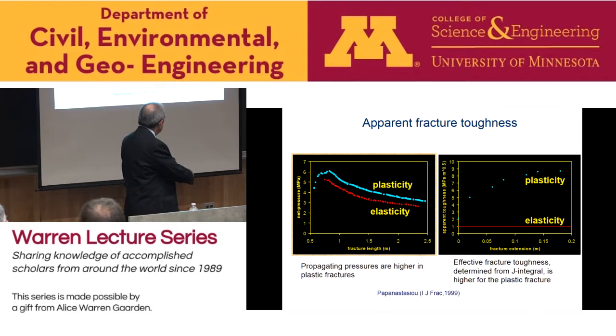And we use one of the energy criteria, the J integral. Basically, we propagated the fracture with a cohesive model, but at the same time, we took contours of J integral, and it was possible to calculate this increase in the apparent toughness. And with elasticity, of course, it's constant, it doesn't increase the toughness during propagation.